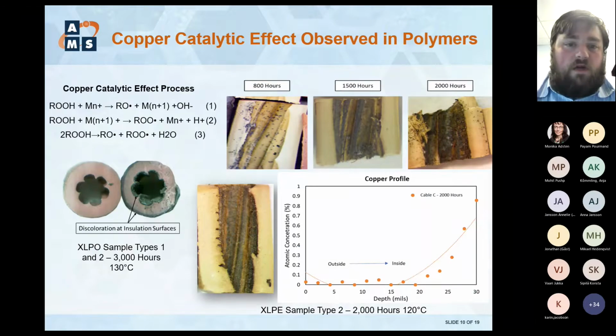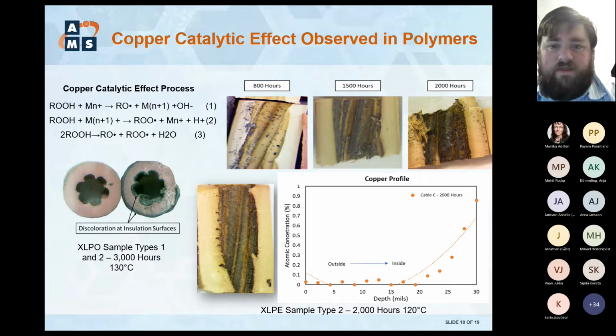Another phenomenon we've observed is copper catalytic effects. So what happens here is, because you're getting oxidation of the copper during the aging process, you're also getting copper ion diffusion into the material at the insulation conductor interface. And that actually catalyzes the oxidation process of the material at that surface.